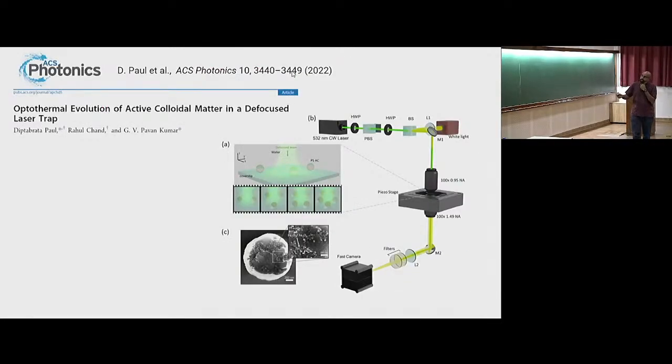One of the ways to do this is the following. You take, let's say, a normal dielectric material and infuse it with light absorbing particles. In this particular case, you can take a polystyrene sphere and infuse it with some iron oxide material. This iron oxide material is then subjected to optical trapping forces. In this particular configuration, again, we utilize a specific orientation of the structure so that you study the evolution of this assembly, where you now have radiation forces. In addition to those radiation forces, you also incorporate an absorption effect.